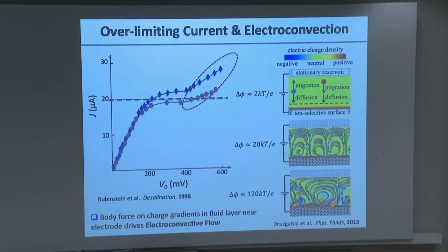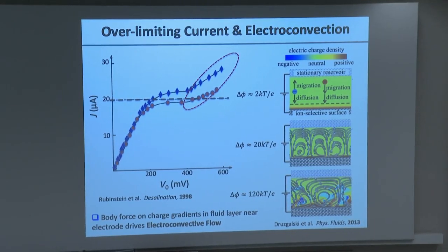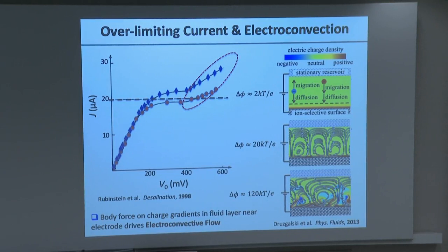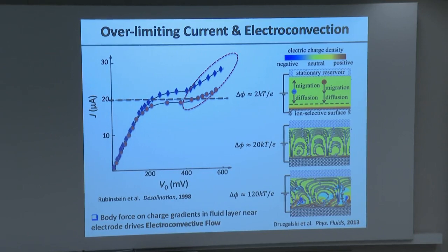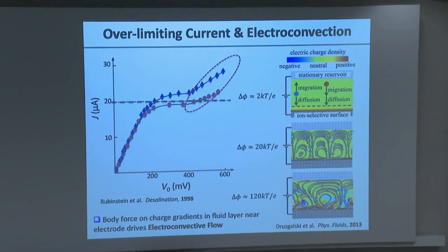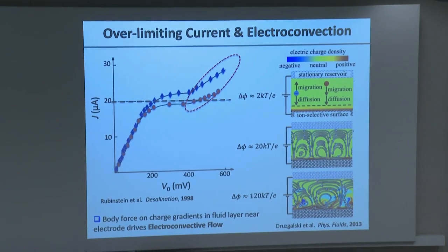And in fact, when you look at the chaos and the time dependence, it looks very much like normal fluid mechanics, so-called inertial turbulence. But this kind of turbulence is coming from the right-hand side of the momentum balance equation, right? It's coming from the coupling between the electric field and the charge distribution, whereas the normal turbulence comes from the left-hand side, which is from the nonlinear term, the V grad V term, in the momentum balance equation. So this was an eye-opener that says that even in a system that is at flow fields well below what you would consider laminar, it can become turbulent in an electrochemical setting.